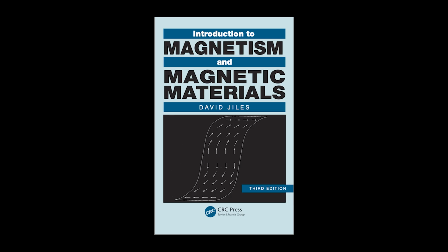That idea of the domain wall breaking free from a pinning site, it sounds violent and sudden. It sounds like it would lead to a discontinuous change in the flux. It does. Can you actually measure that? You can, and it's one of the most remarkable phenomena in magnetism. The Barkhausen effect. Heinrich Barkhausen discovered this almost 100 years ago with an amplifier and a speaker. A speaker? Yes. When a domain wall suddenly breaks free from a pinning site, the flux density changes discontinuously.